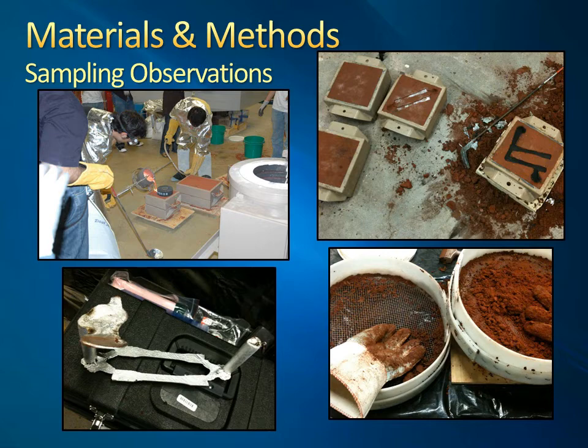The outer door was opened right after the pour to reduce the amount of smoke inside the room due to the lack of ventilation. Participants complained that without the outer door being opened, the haze would never fully dissipate. Even with the outer door open, the smoke and odor lingered in the room for several hours after each pour. Before the sampling period was completed each day, the room was swept to contain the spread of the green sand back into a pile near the pour site, possibly spreading smaller particles back into the atmosphere. Every morning at the start of the sampling, a very thin layer of reddish dust was visible on the floor and the surfaces of the sampling area.